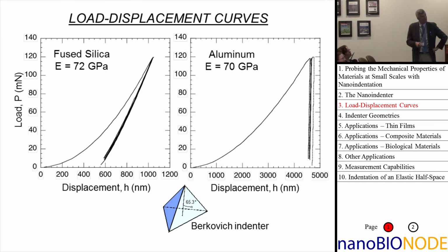As you push that indenter in, that is a sharp, geometrically similar, self-similar object. As you're pushing it in, you are elastically and plastically deforming the material, so you're making the permanent hardness impression. As you unload, in this material, you're recovering the elastic portion of the deformation. You know that's elastic because if you reload and unload, and that's done 4 times in this one, it perfectly repeats itself. It's perfectly reversible, or elastic, deformation. And the point is that by having a loading curve and an unloading curve, you have information about elasticity and plasticity. There are basically 2 equations and a couple of unknowns, so you can use the data in those curves to extract basic information about elastic and plastic properties of the material.